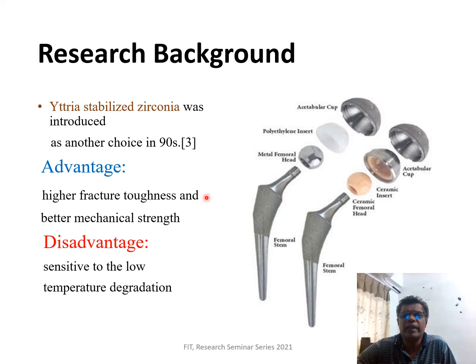But although it has this very good advantage, it has another disadvantage. This material is very sensitive to low temperature degradation. So when it goes to low temperature, what happens? The zirconia grain size starts to grow, and when it grows, the surface of the yttria stabilized zirconia becomes more rough and causes failure. So with low temperature degradation, it becomes more rough and loses its mechanical strength. The mechanical strength gets weaker when the grain size gets larger. This structure shows the hip ball made of zirconia.